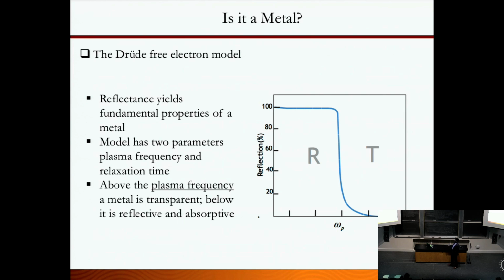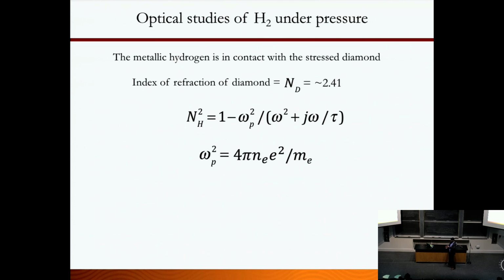From there you can get the plasma frequency and the relaxation time, and you can calculate the conductivity. Below the plasma frequency it's reflective, and above the plasma frequency it's transparent. The diamond is touching the hydrogen sample right now. So you have metallic hydrogen, and on top of that you have a diamond layer. The refractive index of diamond is 2.41, so using that, you can get the reflectivity of hydrogen. Hydrogen reflectivity is given by this equation. You have plasma frequency, relaxation time, and you substitute here, and n_D you know, 2.41, and then you can fit this to the Drude model.